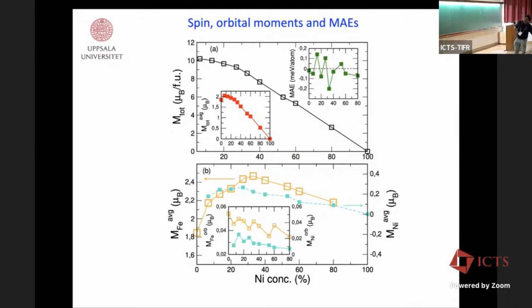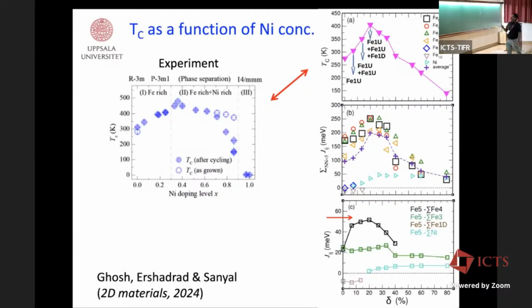And the important thing is actually the calculated TC as a function of nickel concentration. So you see that we also have a similar behavior.